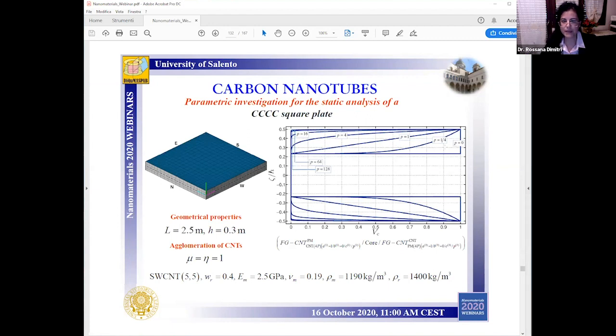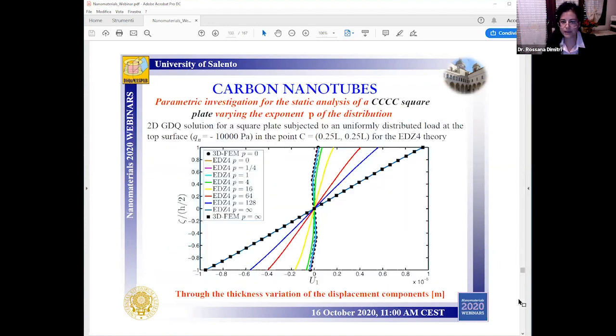So note that for P equal to 0, the example reverts to a laminated structure made of carbon nanotube uniformly reinforced layers of equal thickness. And on the other hand, when P tends to infinity, the plate is completely made of polymer matrix. So in this plot, see the through-the-thickness variation of the displacement components and look at the zigzag effect in the kinematic response when P is equal to 0, typical of a laminated structure. And for higher values of P, the structure tends to an isotropic plate, since the soft core effect reduces gradually. So the two limit cases are also obtained by using the 3D FEM model in Straus7 in this case, while the intermediate values of P get a smooth variation in between.